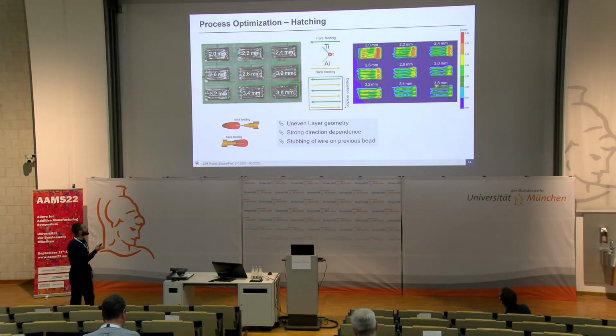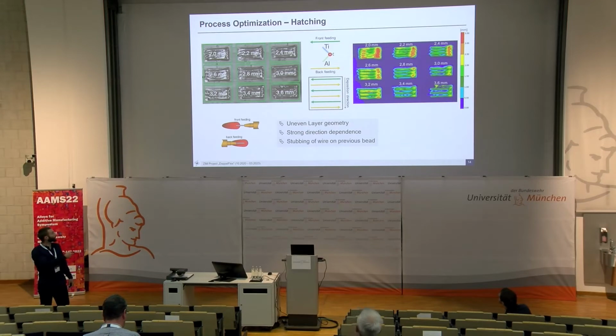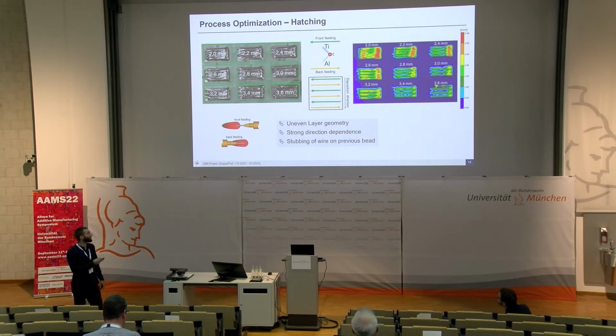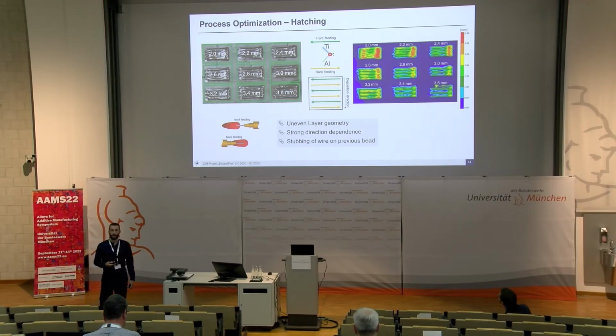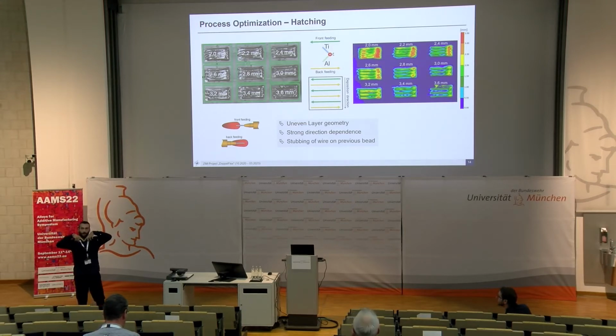So we tried some hatchings. The first hatching was front and back feeding, alternating. Here we see a picture of the measurement, an optical measurement with a GOM system. We see a pretty uneven layer geometry. In the middle it's pretty flat, on one side it's pretty high. That's because of the strong direction dependence of the process. We also have a stubbing of the wire on the previous bead, because we approach at a 45-degree angle to the build plate and with a 90-degree angle between those two wires.